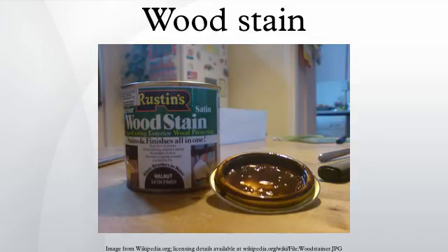Preparation: typically, a thorough final sanding of the wood with one suitable grit will even out the absorption of the stain. Wood stain on a bare softwood or oak floor might require a final prep sanding by hand or with an orbital vibrating sander with 80 or 100 grit, whereas certain hardwoods might be orbitally or hand sanded with 220 grit and higher for a darkish organic stain on furniture.